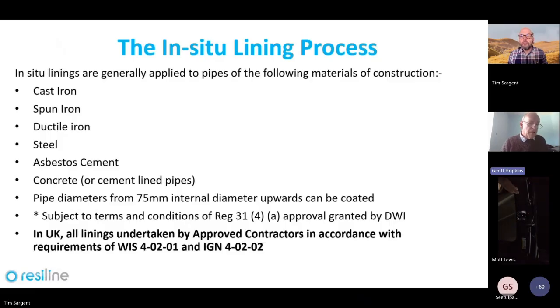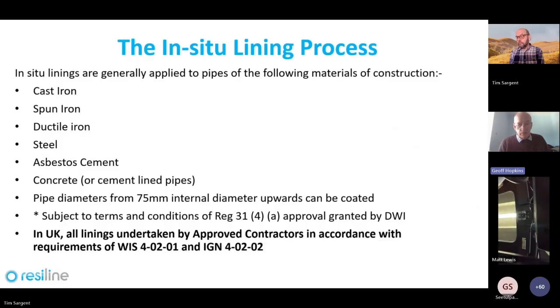Okay, in the UK, the approvals generally relate to lining non-organic pipes. We don't tend to line PVC pipes because the failure mode is longitudinal split, so you need fully structural linings for that. So probably not the best use of it, but cast iron, spun iron, ductile iron, steel, asbestos cement, and cement or concrete or cement lined pipes. In the UK, we can spray line pipes from 75 millimeters diameter upwards, good old 3-inch pipe. All the linings approved have to be applied in accordance with their conditions of use, which are granted by the DWI, and approved contractors have to be used who comply with water industry specifications.